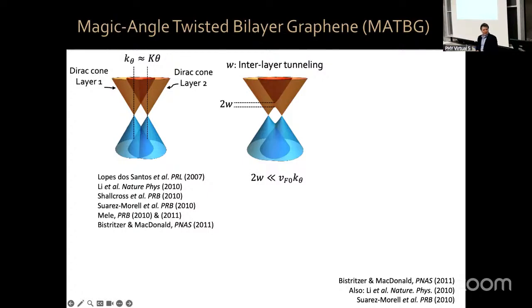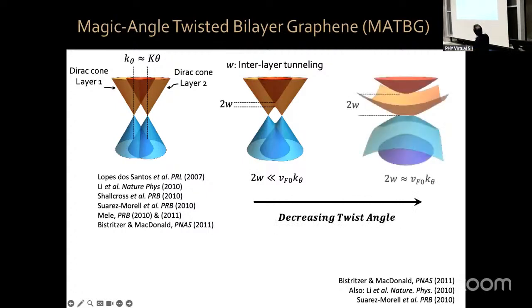If we decrease the twist angle, we make those two Dirac cones get closer and closer to each other. And therefore, at this crossing point of the Dirac cones, the band repulsion pushes them towards lower and lower energy, the closer they get. As a result, as we decrease the twist angle, there is some angle for which this lower band, pushed down in energy, gets pushed all the way to zero.